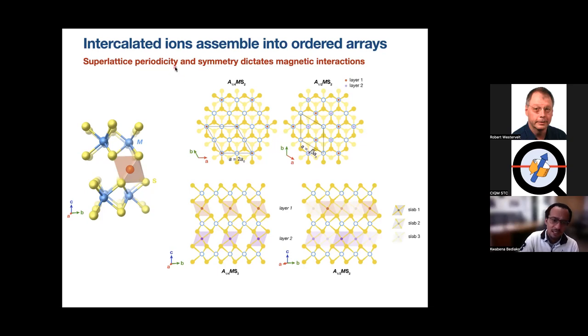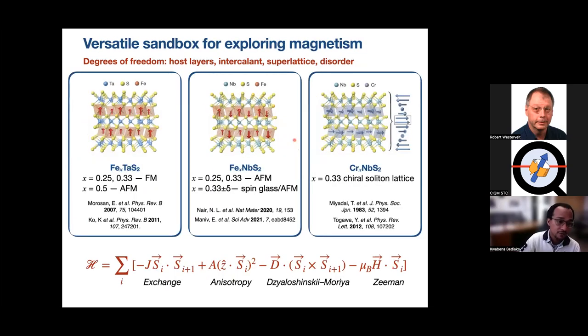And so in transition metal intercalated TMDs, you have intercalated ions that assemble into all kinds of ordered arrays that lead to a rich variety of physics: ferromagnets, antiferromagnets, and spin glasses that can switch the antiferromagnetic domains. This is work from James Analytis's group here at Berkeley, and you should, if you haven't already, have him out to give a talk on this material. And then even some really interesting helical magnetic states. And then there's this interplay between all these different energies in these systems.